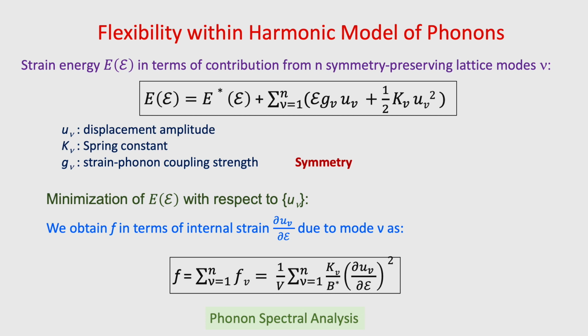So the key point is the coupling between strain, which are acoustic phonons. I explained to you that those are the ones which give you sound waves, and optical modes. So internal strain and deformation strain, they couple together to give you flexibility. Okay, so if you work out this expression, you will find out that this is the phonon contribution